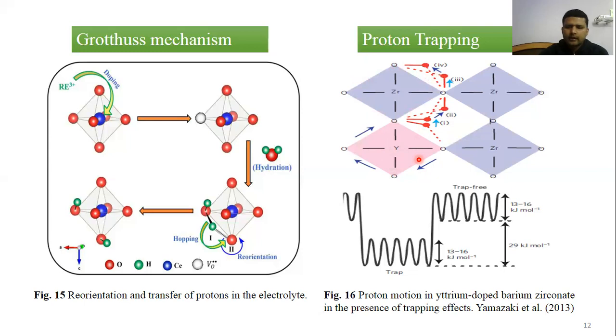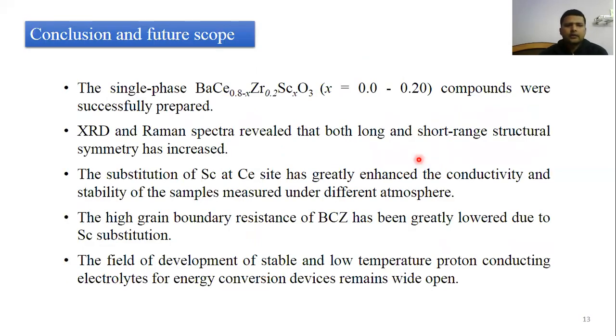In 2013. So in conclusion and future scope, we have successfully synthesized single phase compounds, and Raman and XRD spectra reveal that both short range and long range structural symmetry has increased. The substitution of scandium at the cerium site has greatly enhanced the conductivity and stability of the samples measured under different atmospheres. The high grain boundary resistance of barium cerium zirconium has been greatly lowered due to the scandium substitution. The field of development of stable and low temperature proton conducting electrolytes for energy conversion devices remains wide.